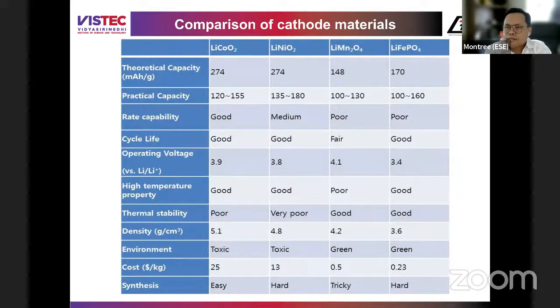And for a comparison of the batteries, we mostly look at the cathode material because at the anode, we have only one or two options, like graphite, which is the best anode material. But for the cathode, we have a lot. For example, LFP, like GPSC and the companies use, has a theoretical capacity. You can see milliamp hour, the current times hours, actually the unit of the charge of electrons, we call capacity, normalized by the weight of the material, right? LFP is about 170.